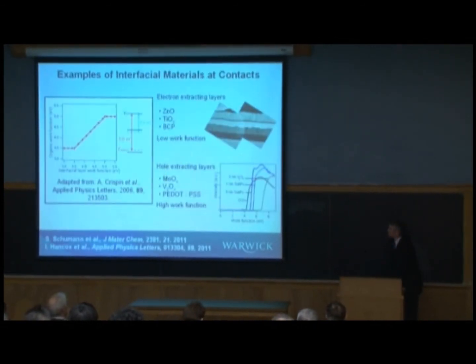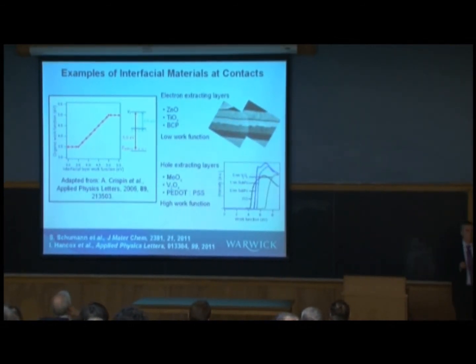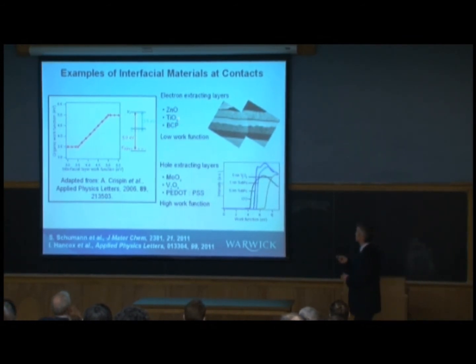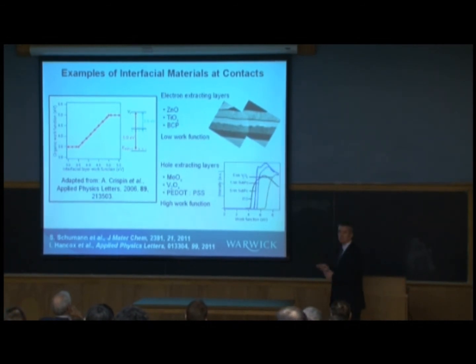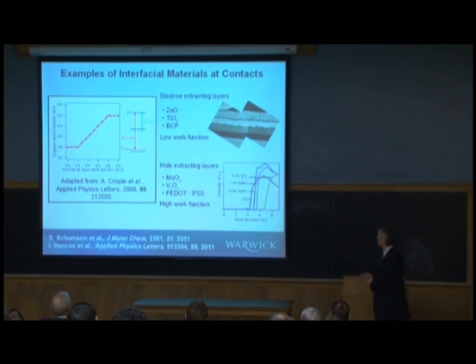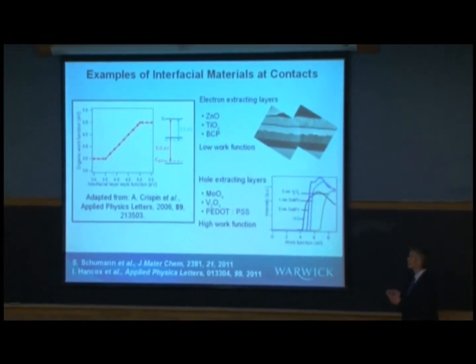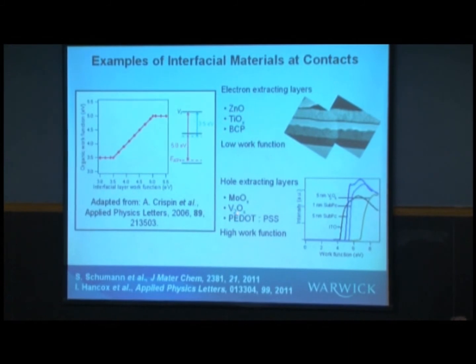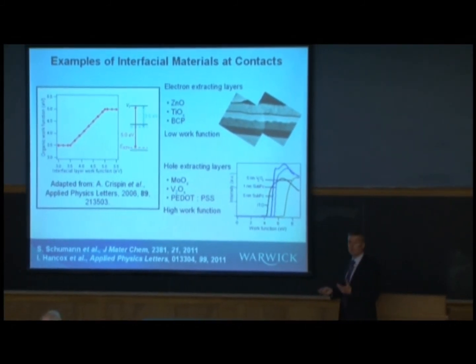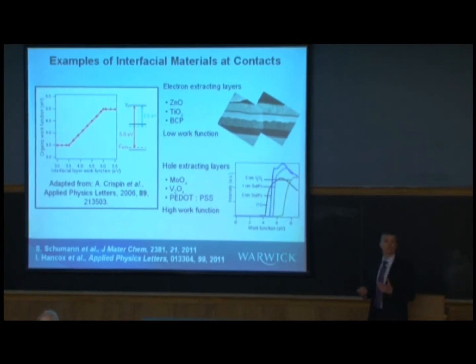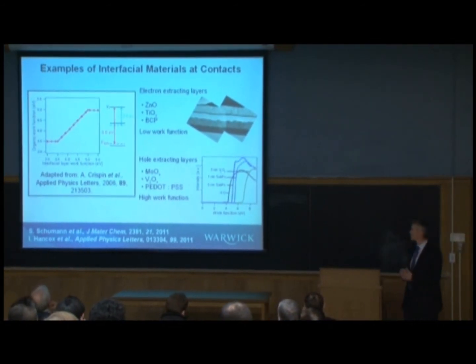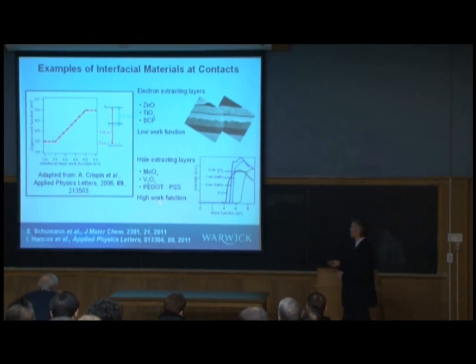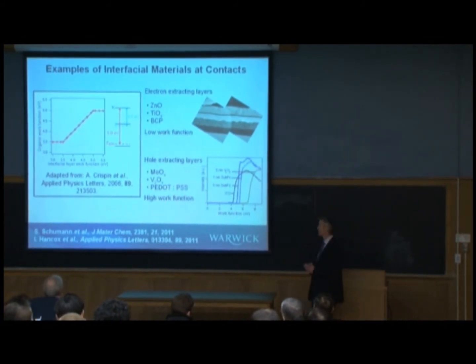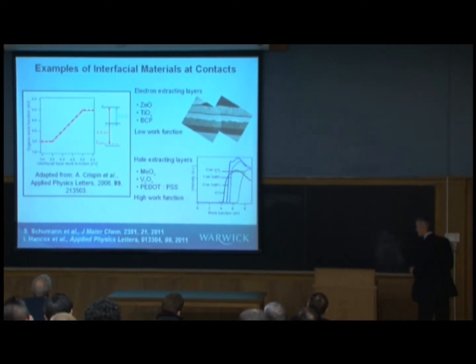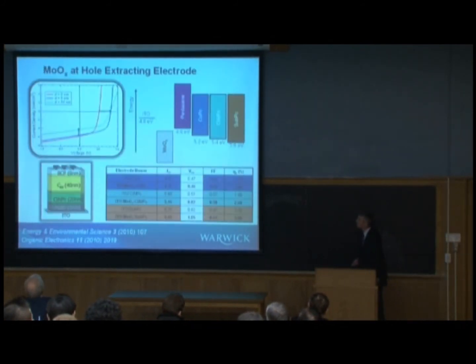Now there's a number of different materials you can use for making more efficient extraction of charges at those electrodes. For example, for electron extraction, you'd use materials such as zinc oxide, which is very efficient and works very well, titanium oxide, or an organic material such as BCP. To extract the holes, good materials include molybdenum oxide, vanadium oxide, organic materials such as PEDOT:PSS, and again other materials, self-assembled monolayers and so forth. High work function materials are all quite efficient in enhancing this process. I'm just going to show some results for the metal oxides just to show how that works.